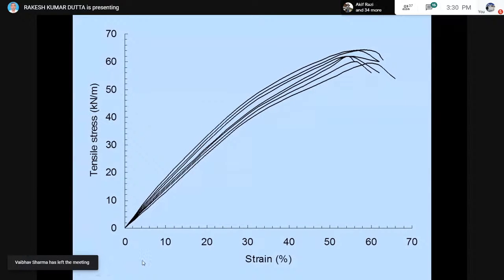So these are the tensile stress versus strain curves. So here you see that if you test the material along the width and along the length of the roll, you will find a lot of variation, and this entire variation in the strength is because of the different diameter of the yarns which are used for making the woven types of geotextiles. So here the yarn diameter is different, and therefore the strength in different directions. Therefore if you test 5 specimens in the main direction of the roll, which we call the machine direction, and 5 across the width, which we call the cross machine direction, you will find a lot of variation in the tensile strength.